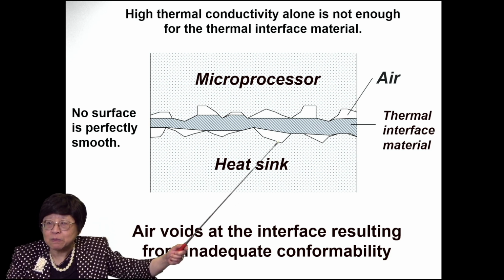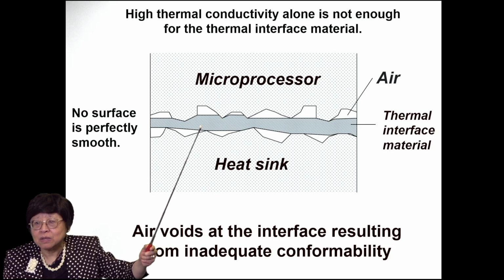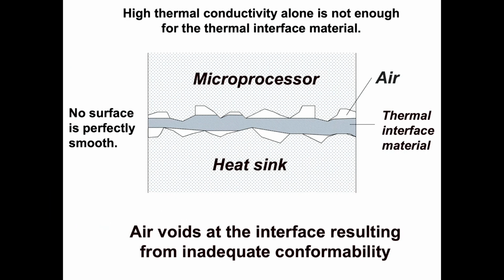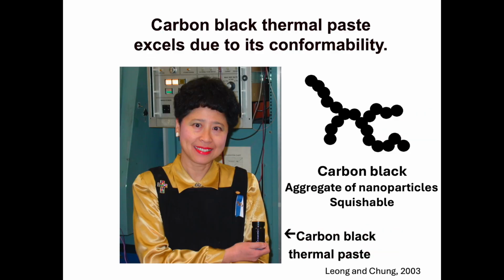So the thermal interface material has to be able to conform to these ups and downs so as to displace the air out. So the conformability is crucial. Even if the thermal conductivity is very high, if the conformability is not good, that material is not going to function well as a thermal interface material. And realizing that and knowing that carbon black is itself a solid that is conformable, I ended up inventing carbon black thermal paste, which excels due to the conformability.